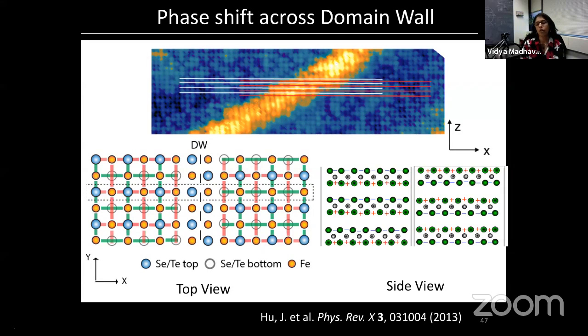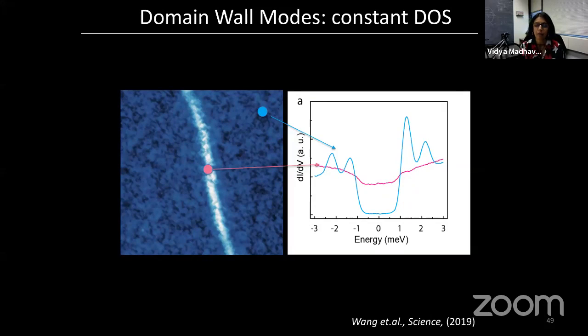So you can find domain walls like this if you search, and then you can go and do spectroscopy on these domain walls. The blue spectrum is far away from the domain wall, and you see these multiple coherence peaks like I showed you before, and a flat density of states. And if you go to the top of the domain wall and you take a spectrum, you see something really curious. You can see the remnants of the superconducting gap, but you see a very flat density of states with a very high density of states inside the gap. So this density of states is very, very non-zero.